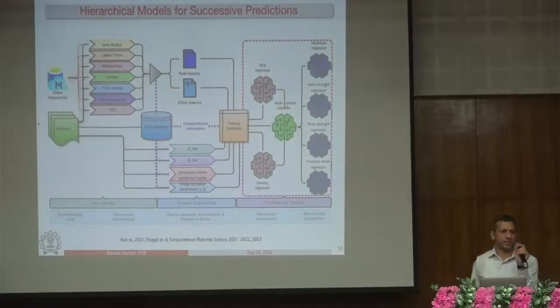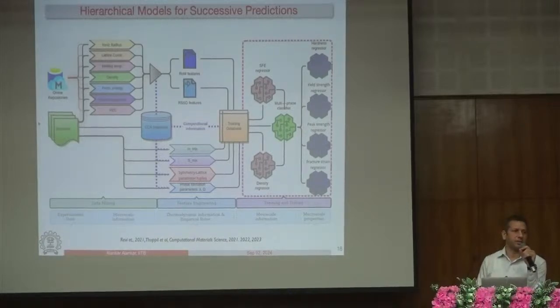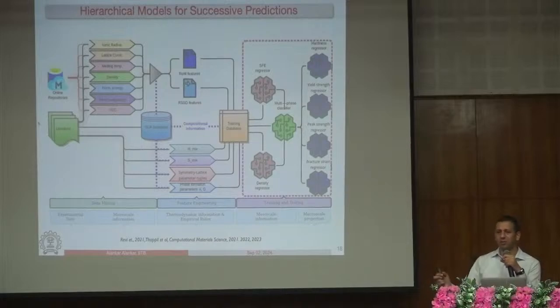stacking fault energy, which is important to initiate plasticity in metals, because stacking fault energy is the one that tells you when the dislocation will nucleate. And dislocations are important for metals. Without that, there will be no plasticity. So we definitely want to understand what the stacking fault energy is. And density is another important property. We do not pay attention to density, saying that it just has something to do with mass and volume. But density also has a very strong correlation with the modulus of elasticity. Why? Because the denser the material, the closer the atoms, and it will take more energy and force to stretch them.